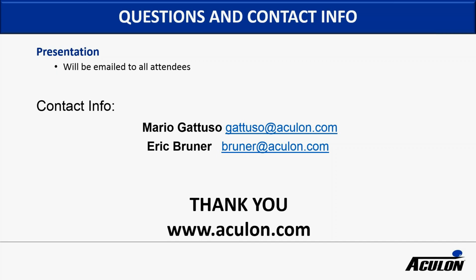Next question is, what temperature can the coatings withstand? So all of these treatments are polymeric in nature. In general, they're stable to about 225 Celsius before they become significantly compromised. And for any sort of long-term exposure, you want to ideally have them below 200 Celsius. We don't see any issues on the low temperature end of the spectrum.